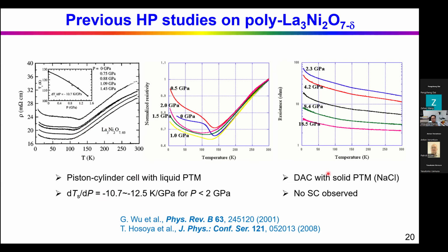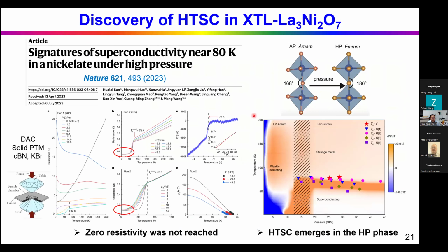And they also used the diamond anvil cell to measure the resistivity at higher pressures. But here they used a solid pressure medium, sodium chloride. And as you see, the resistivity shows semiconducting-like behavior, not metallic at all. They measured up to 18 gigapascal, and there's no signature of superconductivity in the earlier studies. But the story changed last year.